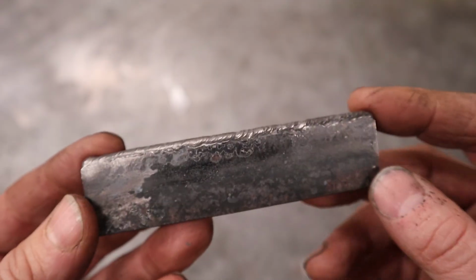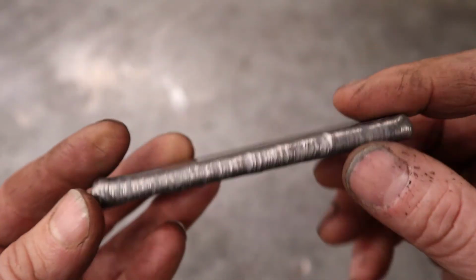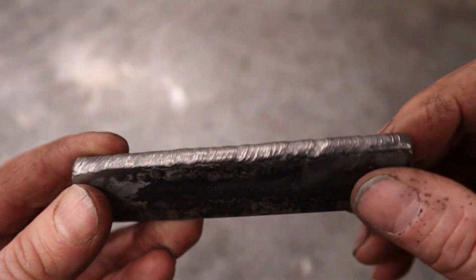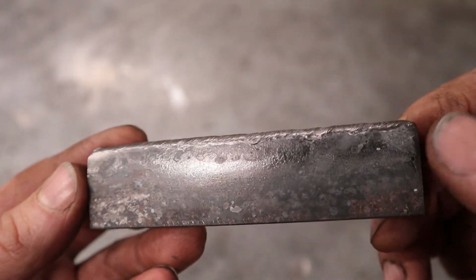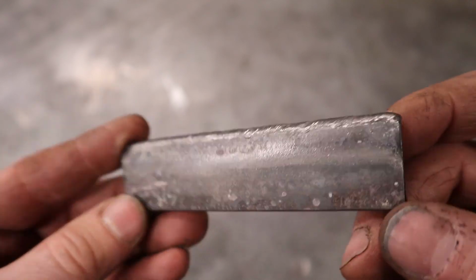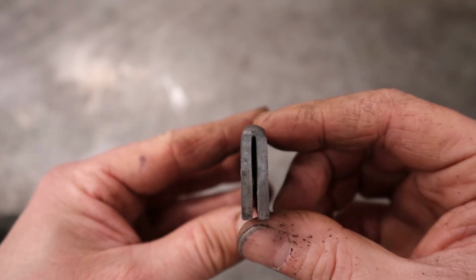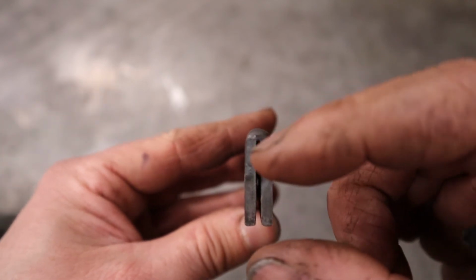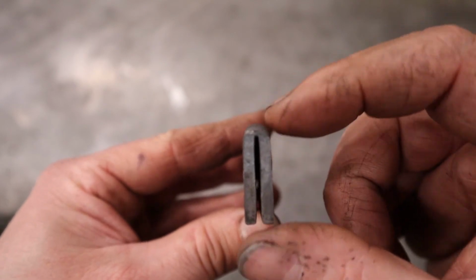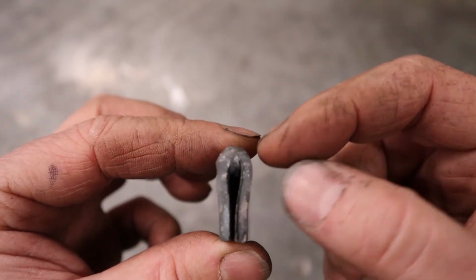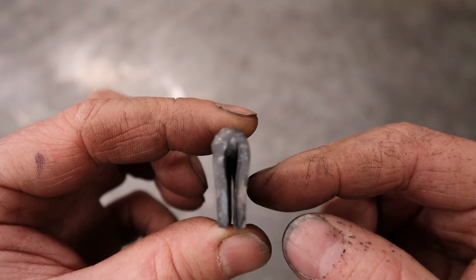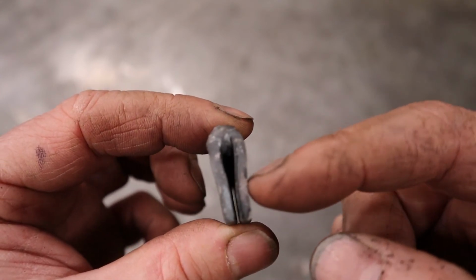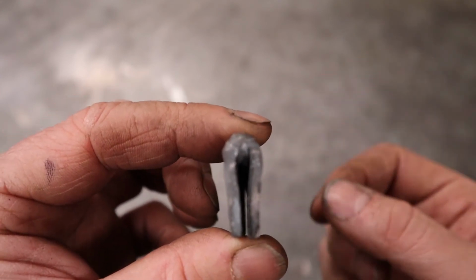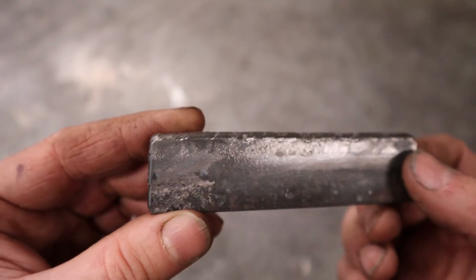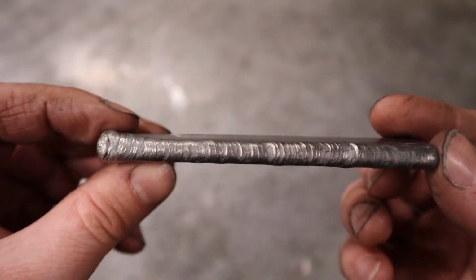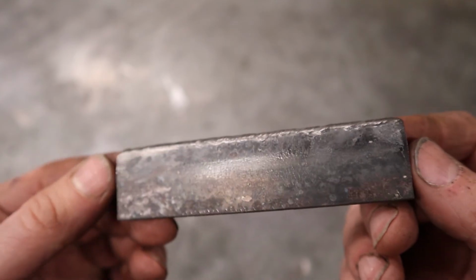As I take a look at this welding sample, along the weld bead, along the edge of both sides and through the top, there's not a single crack or any sign of weakness. Some mill scale came off when we bent it, but if we look at the end shape of it, no cracks, no damage, a nice and strong bend. A little bit of weld was on the inside, so when I tried to squish this in the vise, it actually started bending and deforming the base metal. So once again, that weld bead is going to be stronger than the base metal if done properly. Overall, a nice looking and very strong gas weld.